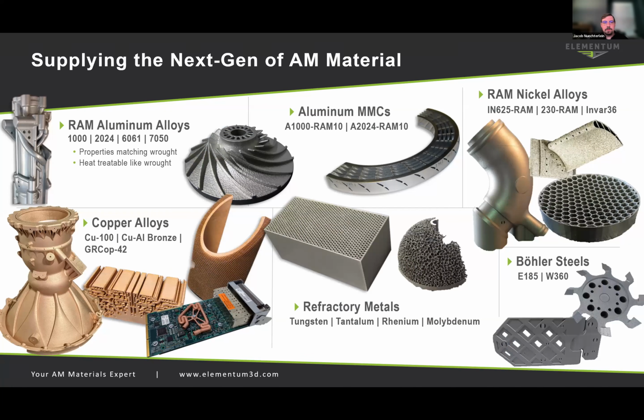There's a number of different alloys that we've been printing, so we're not just printing copper alloys, but I really want to focus in on what makes copper difficult, why, and what makes copper different from some of the other materials. But certainly there are challenges in other materials that I think are completely different. So the solidification structure differences that are in aluminum alloys or nickel super alloys don't really occur in the copper alloys. And that would initially make you think, well, copper then is a good choice. But really it comes down to materials that are hard to weld typically are hard to print. And so finding materials and making materials more weldable is a pretty important part of making them printable.